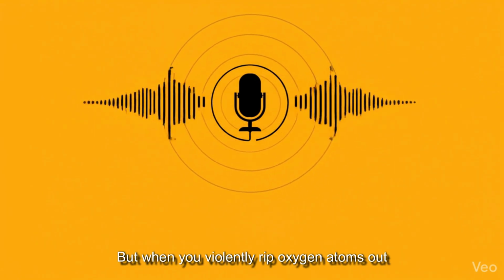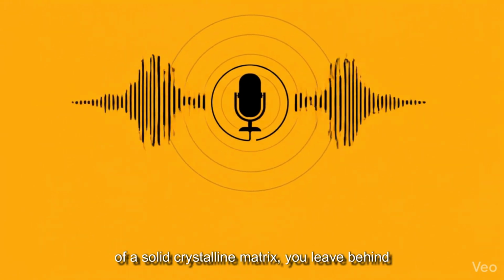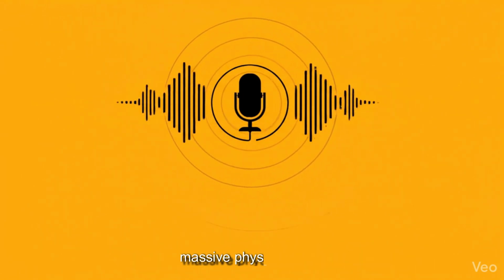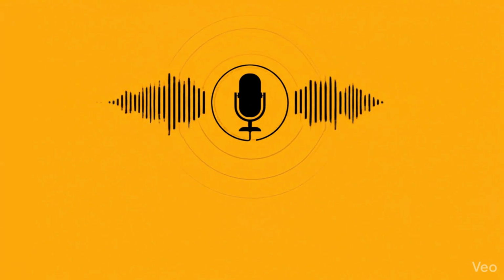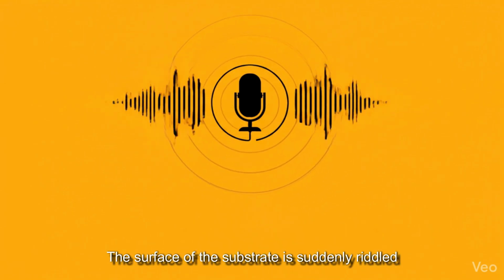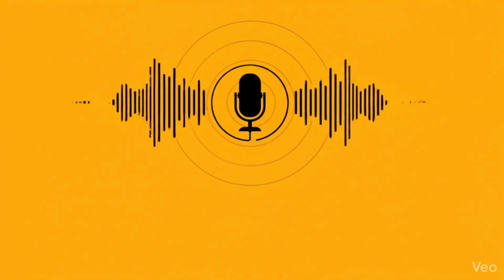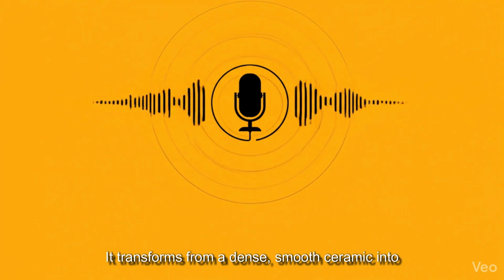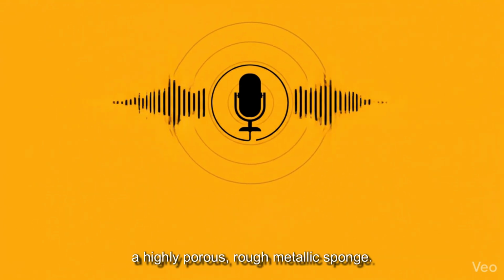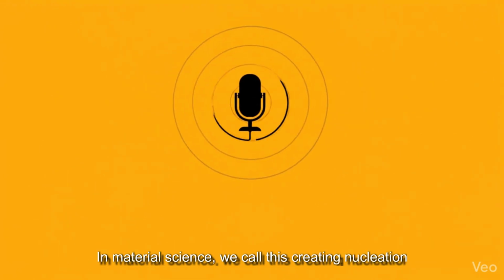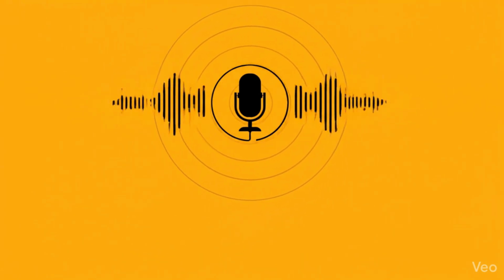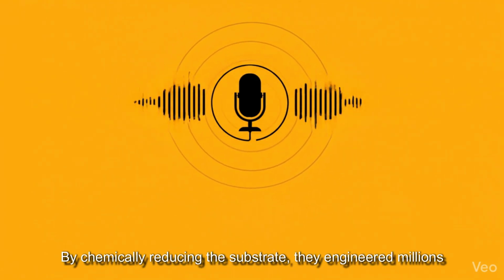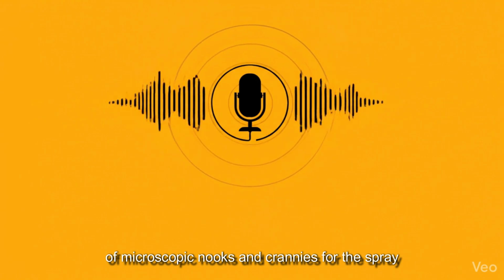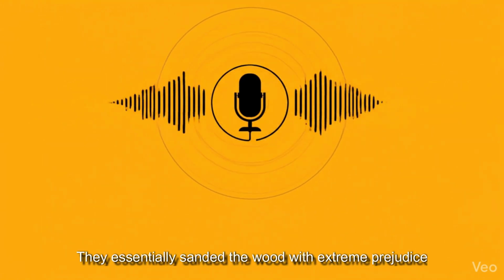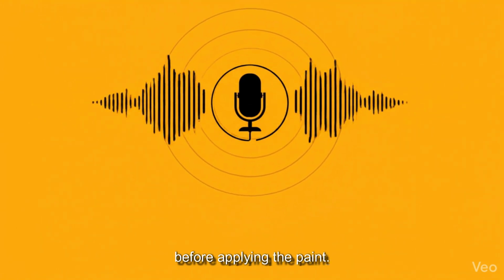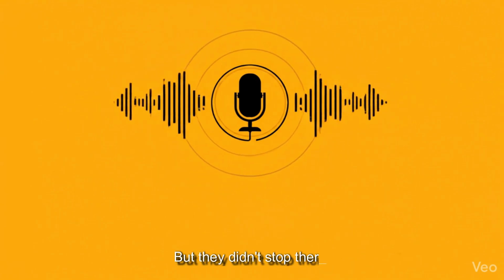But when you violently rip oxygen atoms out of a solid crystalline matrix, you leave behind massive physical voids. Oh. The surface of the substrate is suddenly riddled with microscopic craters. It transforms from a dense, smooth ceramic into a highly porous, rough metallic sponge. In material science, we call this creating nucleation sites. By chemically reducing the substrate, they engineered millions of microscopic nooks and crannies for the spray to grip onto. They essentially sanded the wood with extreme prejudice before applying the paint. Exactly. But they didn't stop there.